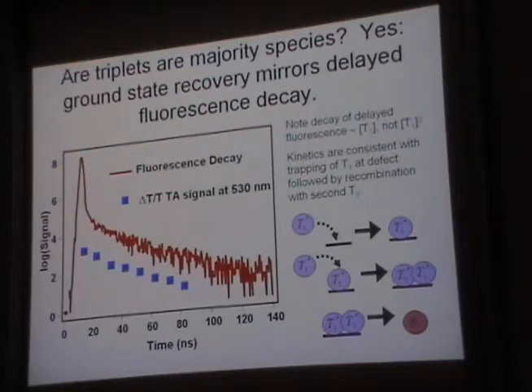Because there's something else there, some dark state like a charge transfer state, as was postulated for pentacene. But if you go and measure the bleach and watch it fill in, that rate of recovery of the bleach, we can get about a decade, a little more than a decade, exactly mirrors the rate of decay of the delayed fluorescence, which we know is the triplets.